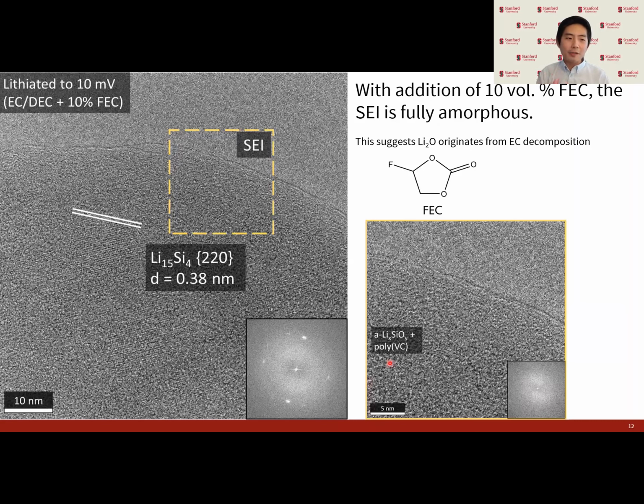Okay, but what we really are interested in is what the electrolyte additive FEC is doing and why it's so important for silicon stability. If we then do the same kind of experiment, lithiating the silicon nanowire, now in this electrolyte with 10% of this FEC additive, we can see that there are changes to the silicon nanowire. So the lithium silicide core remains the same. So the lithiation behavior of the silicon itself is not changing, but the SEI nanostructure is changing significantly. Whereas previously without FEC, we saw lithium oxide in the SEI, now we're seeing a completely amorphous SEI. So that tells us the lithium oxide is coming from the ethylene carbonate reduction.